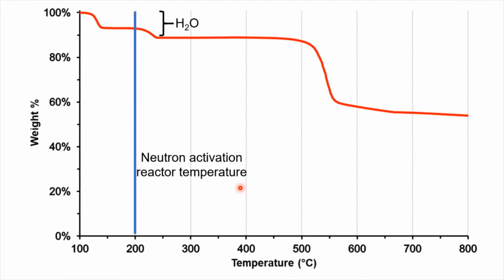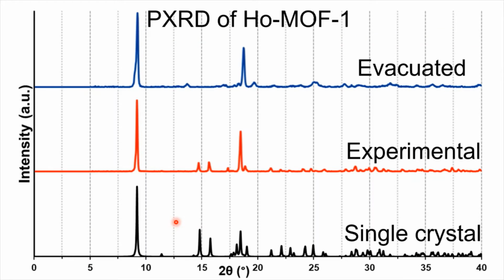Then you run TGA, thermogravimetric analysis, and here you can see these 2 solvent drops. So we know that the material is stable up to 500 degrees. And as I mentioned before, 200 degrees is what we think the reactor gets to. So this is a very promising material. And you finally run PXRD again, just to show that after you do the evacuation, this process of removing the solvents called evacuation, you still have that structure intact.